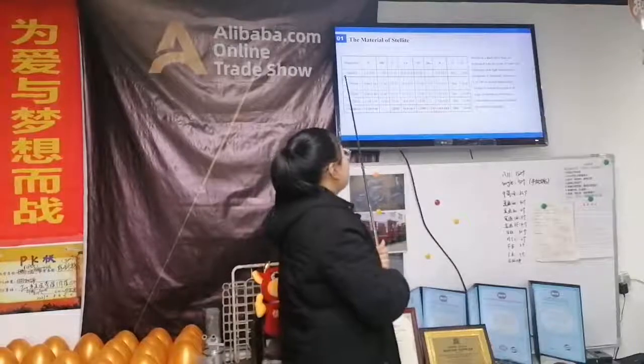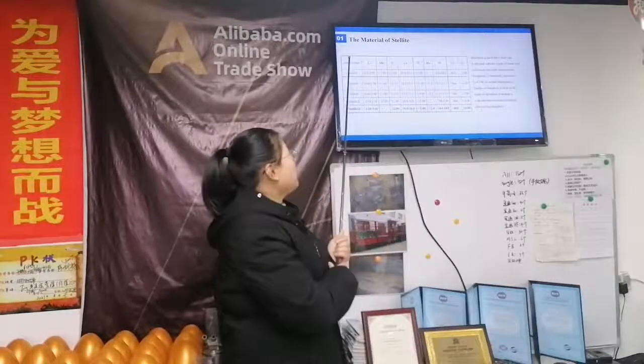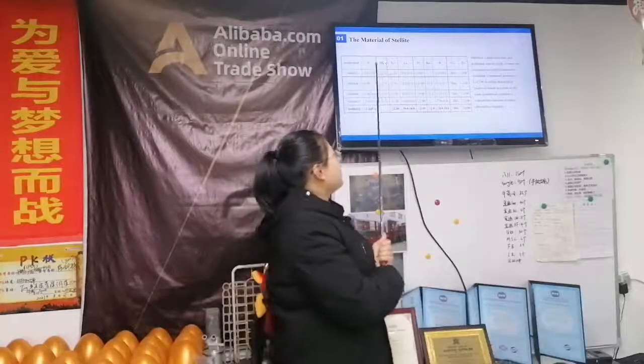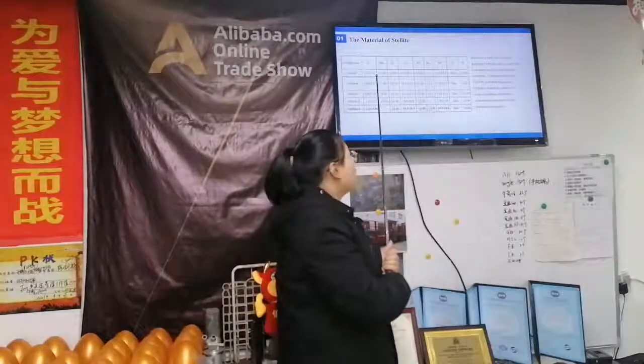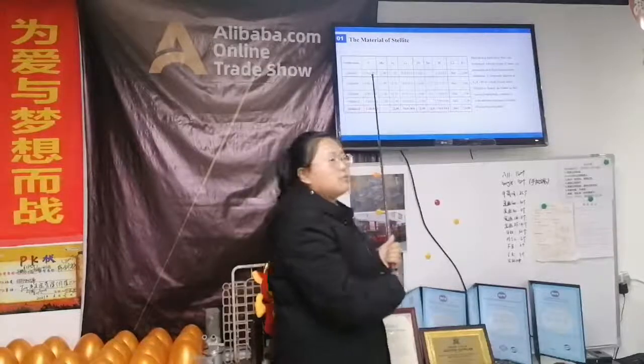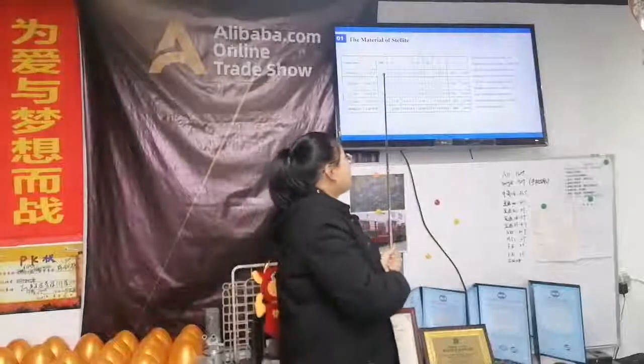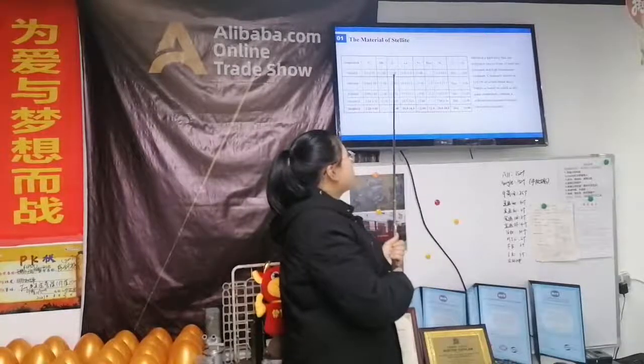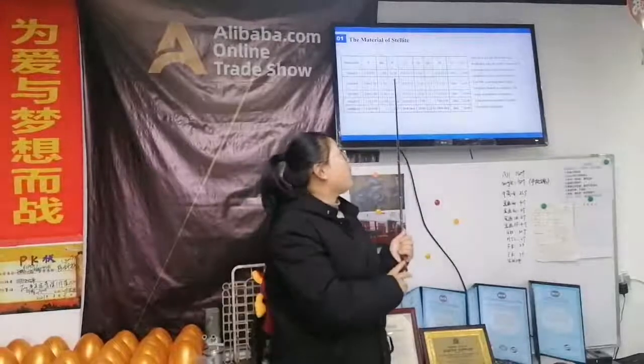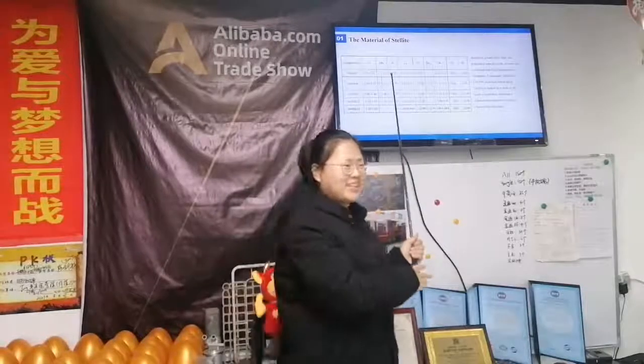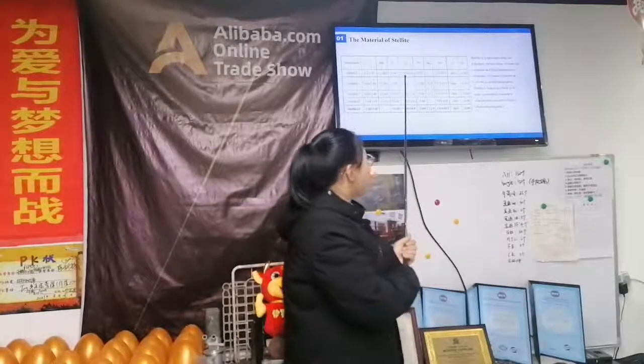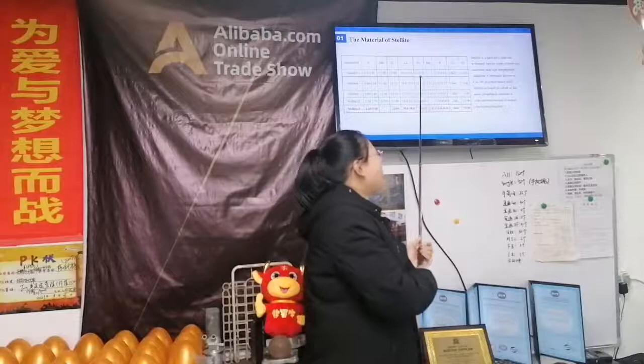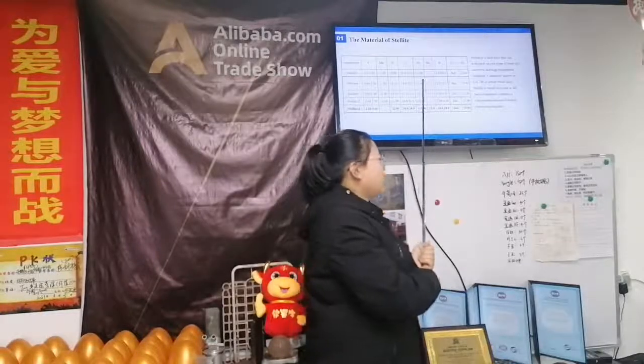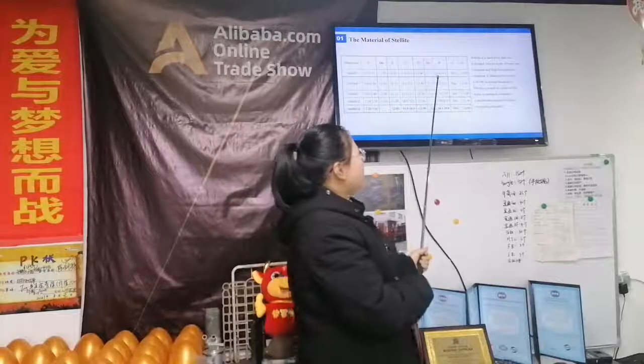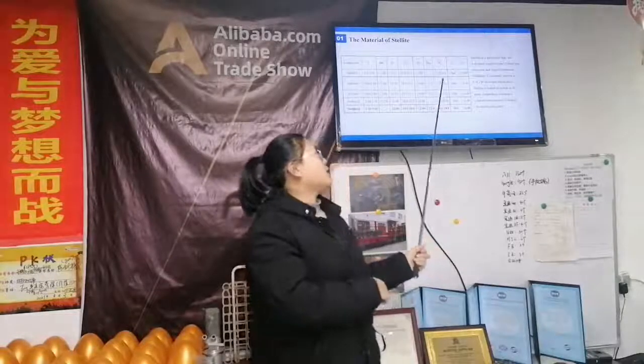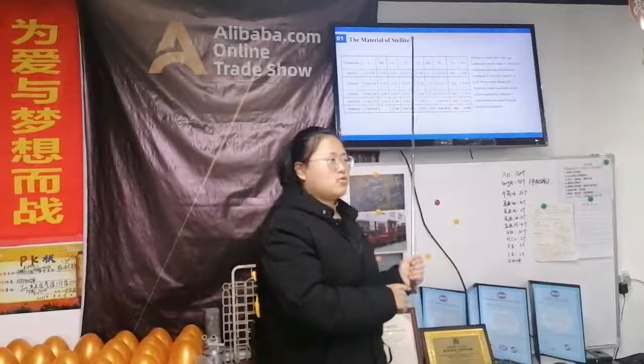You can see the stellite 3. The chemical composition for carbon is 2.0 to 2.7%. For manganese is less than 1%. For silicon is less than 1%. For chromium is 29 to 33%. For nickel is less than 3%. For tungsten is 11 to 14%. And the cobalt is balanced.